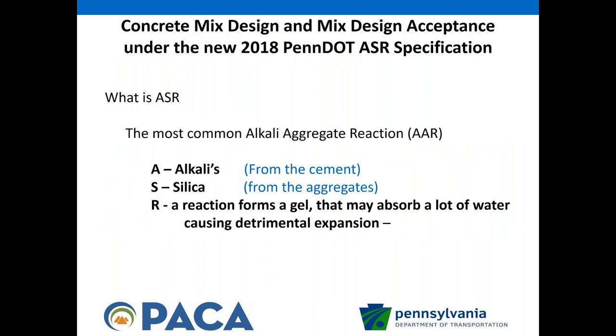A little background about ASR. The A stands for alkalies — they come primarily from the cement, and those are what we're most worried about. The S is for silica, which comes from the aggregates. It has to be the right kind of silica. If you have enough alkalies in the cement and the right kind of silica in the aggregate, they can form a reaction and form a gel. If that gel is the type that absorbs a lot of water and water is present, you can have some very detrimental expansion.